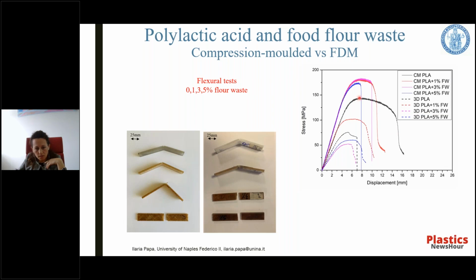but this parameter doesn't vary significantly as the filler content varies. On the contrary, we can see here, for the samples obtained by 3D printing, the filler seems to have a non-monotonous effect on the maximum load, and in any case, not significant compared to the matrix one, that is, in this case, the black one. Unlike the tensile results, for the samples containing 1% of filler weight, that are the red line, a notable performance improvement was recorded.